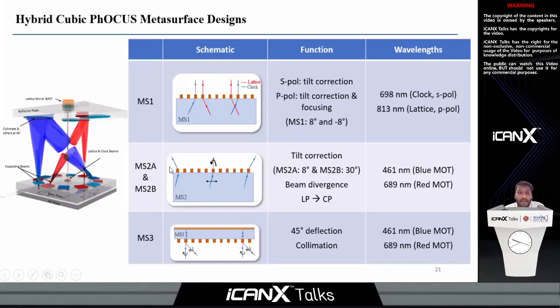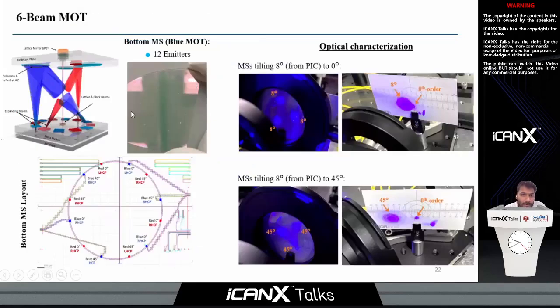So indeed you can design and fabricate these. Shown here is the PIC plate. If you look at this drawing in the center, these dot marks are hundreds of microns in diameter, and these are the metasurfaces, these Lego blocks, and they can do the function that I just talked about. If I shine light on one of these dot marks on this plate and look at the beam in the far field, then what you see are these diverging beams coming out, which are circularly polarized, or beams that are sent at 45-degree angles, also with circular polarization.